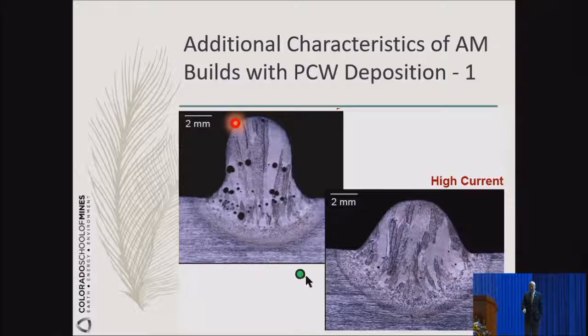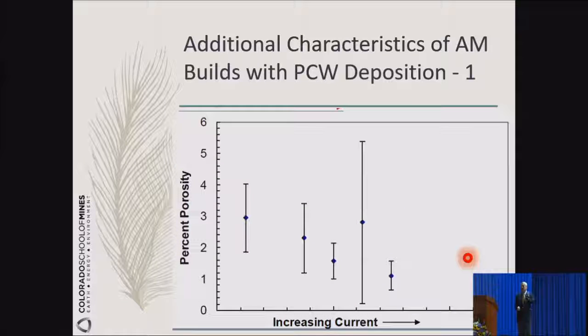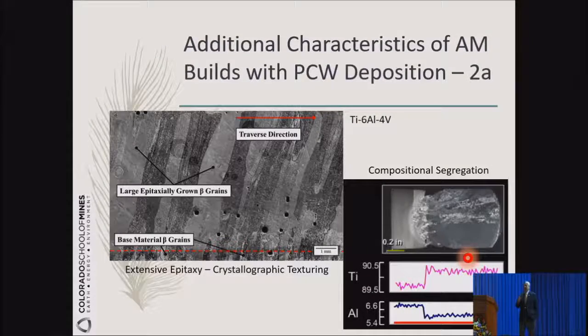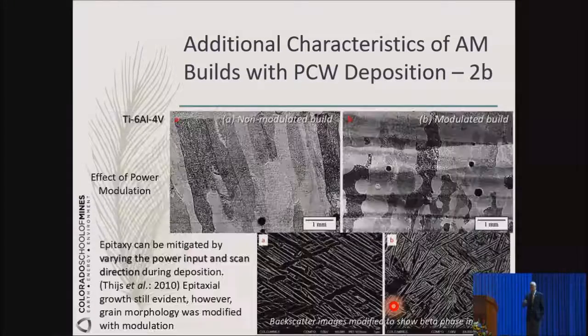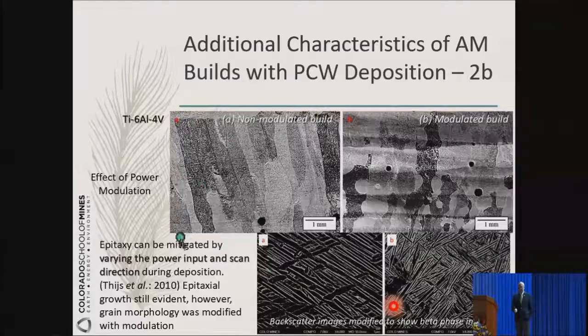So here you see a lot of pores, and here you don't see any pores. The change is only the current. So using process parameters can correct for these properties, okay? And in fact, here's a graph that shows you decreasing amount of porosity with the current level. So it is possible to mitigate all these. Now, another possibility to mitigate is by modulating the current. So instead of using a continuous current, what if I use my electron beam by pulsing the current? Okay, so I'll skip to the next one. This one here only shows you the presence of the chemical composition segregation, okay? So the next one here, you see on the left-hand side the continuous epitaxial growth. On the right-hand side, you still see some epitaxial growth, but those grains are beginning to get broken.